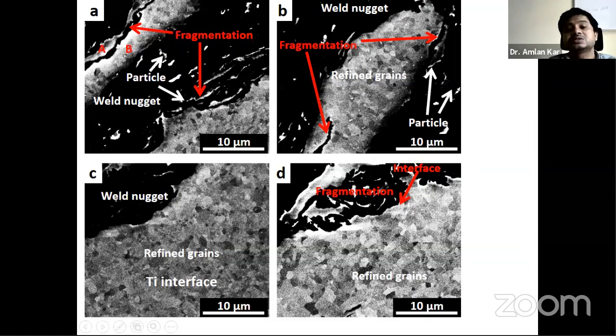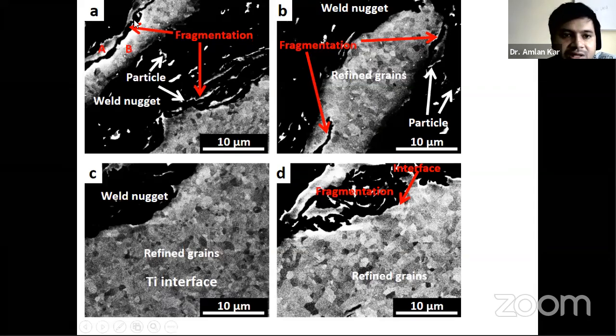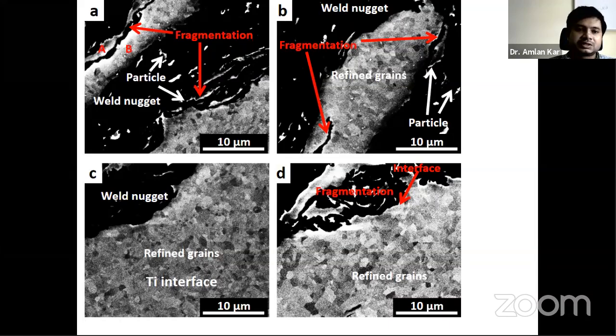Otherwise, there could have been gross deformation or elongation further. Here you can see a crack has developed inside the particle, and that led to the formation of a particle. You can see there is fragmentation, and from the geometry you can see that this is the particle which is developing from the original particle. And this is another example from the geometry. You can see two particles, and this particle is forming or separating out from the original particle. So this is the mechanism.